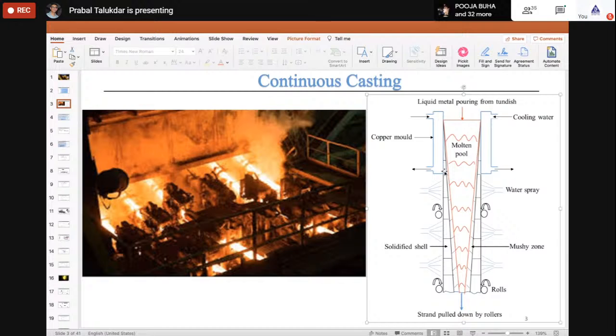There are thumb rules, but they don't work for all kinds of molds. So our intention was to find out an appropriate taper, so that the air gap between the mold and the solidified strand is as minimal as possible. Because if you put more taper, then also there is a problem. If your taper is large, then again it will give pressure on the solidified strand, and in that case you will again get cracks in the billet. So your taper should be as perfect as possible, so that there is no air gap, and no additional pressure from the mold on the solidified billet.